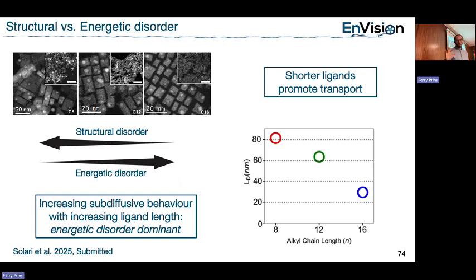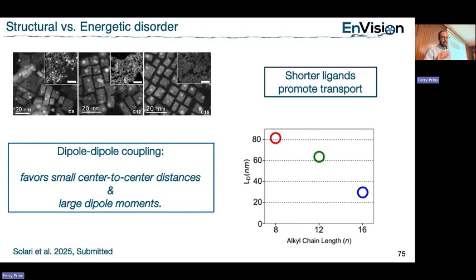Okay, so of course the key here is that these are excitons, so you should not care about the ligand length - you should care about the distance between particles. That's important, right? So if I have smaller particles, it should be better. It's not. On top of that, if I make a smaller particle and it's more excitonic, I also should have a larger dipole strength, which again should promote transport.